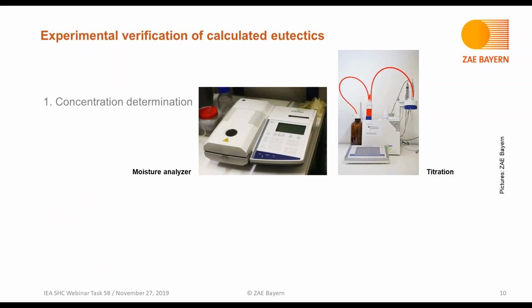So having predicted these eutectic compositions, it's important to experimentally verify the calculations. At first, it's important to determine the concentration of the salt solutions we are measuring. Therefore, we determine the water content using either a moisture analyzer or titration. A different type of titration is also used to measure the concentration of different salt ions. Then, having verified the concentration of the salt solution, we are performing calorimetry.